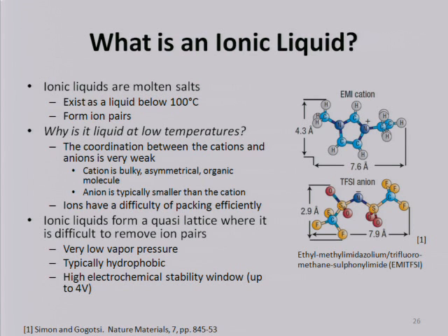And one of them, either the cation or the anion, is one of these complex organic molecules. And it's because we have these huge, complicated molecules that the thing will not solidify. There's, if you will, a steric hindrance to the solidification. So that's why it's liquid at room temperature in some cases, certainly below 100 degrees Celsius.